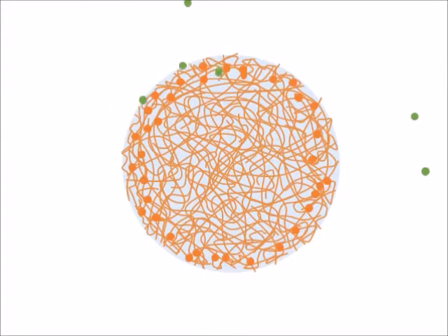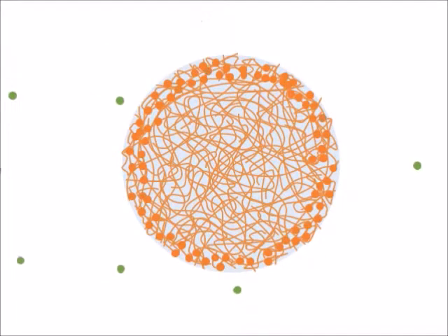Of course, this cross-linking starts from the outside of the hydrogel droplet, but the calcium ions try to penetrate deeper inside. However, on their way inside, they encounter alginate chains and undergo the cross-linking reaction. The more the alginate chains become cross-linked, the more impermeable the hydrogel becomes. At the end, this leads to the formation of a hydrogel shell around the droplet that does not allow further calcium penetration. The calcium ions bounce back and we have obtained a droplet with a solid shell but a liquid interior.